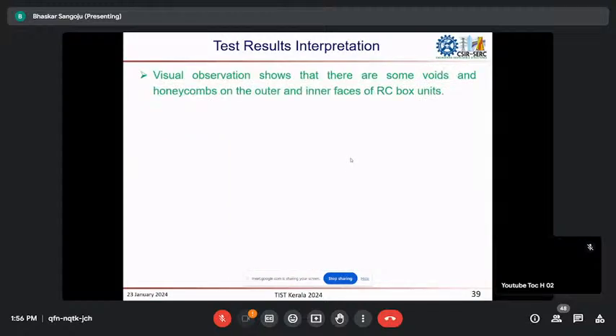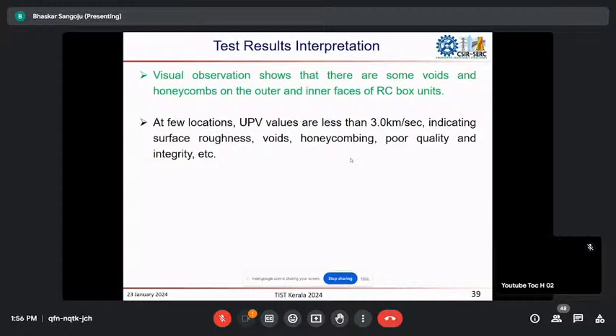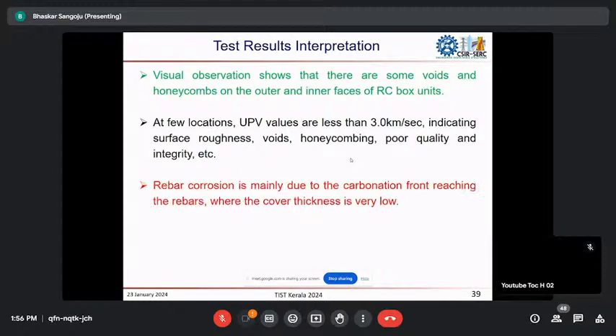That is where the importance of cover thickness and the quality of cover concrete comes in. These are the observations: there are some voids and honeycombs and also inadequate cover thickness. Because of the variability in the concrete quality, the UPV values have varied. And rebar corrosion was observed in some places where the cover thickness is very low.